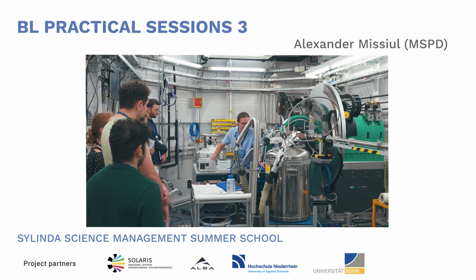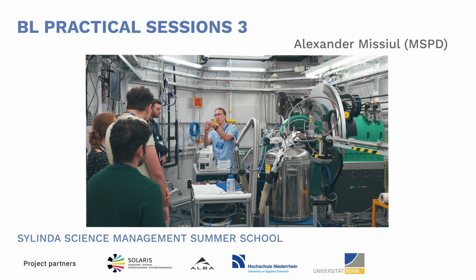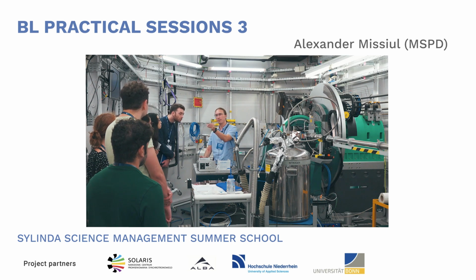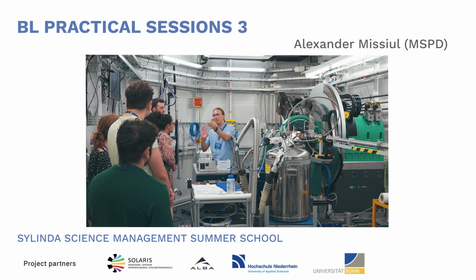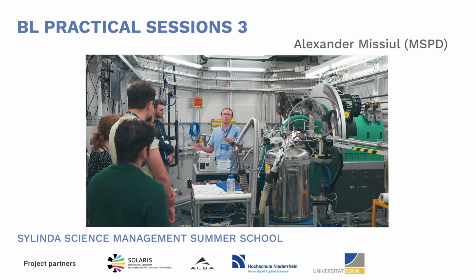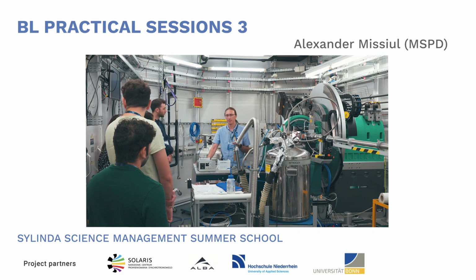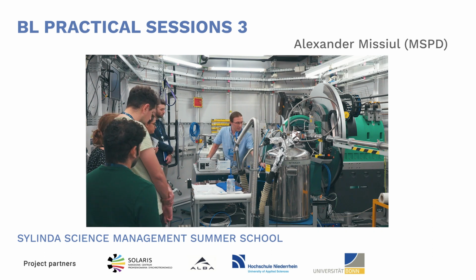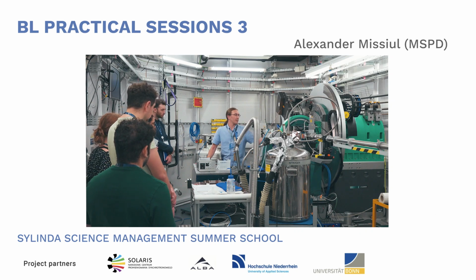So the sample itself here looks like this. We put the powder inside a capillary. The diameter of the capillary can be different, again, depending on the sample. We normally measure in the range from 0.3 millimeter to 1.5 millimeter. Then the capillary is mounted here and put under the beam. The beam size here is 3 millimeters horizontally, and depending on the experiment, from 0.7 to 1.5 millimeters vertically.